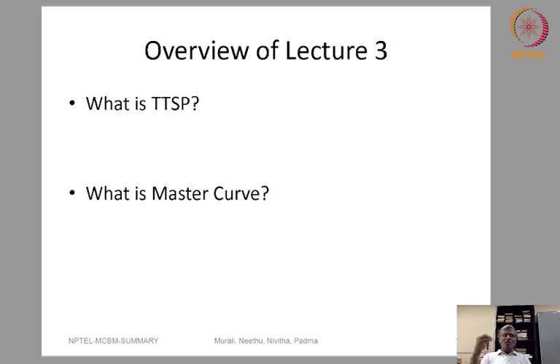Now, for this, we have to construct a master curve. When you construct a master curve, you also need to write something about the shift factor. There are many shift factor functions that are available. The most common ones are the Williams-Landel-Ferry shift factor as well as the Arrhenius type shift factors. Once you have the shift factors, by shifting the curve from the reference isotherm to any other given isotherm, you will be in a position to construct what is really called the master curve.